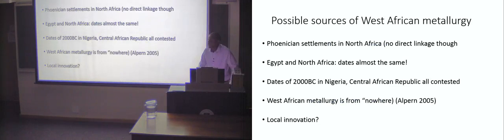So the key question is, can you have iron smelting before copper smelting, given that the technology associated with iron smelting is a little bit more complex? Complex in the sense that the required temperatures must be higher, at least within the region of 1,200 degrees Celsius. For copper, the melting point is 1084, so slightly above that you could smelt copper, but for iron the temperatures were a little bit higher, 1,200 and so on. And remember that it was a solid state reduction, because the melting temperatures for iron are within the region of 1,500 plus degrees.